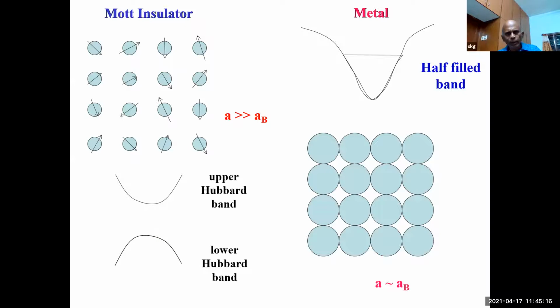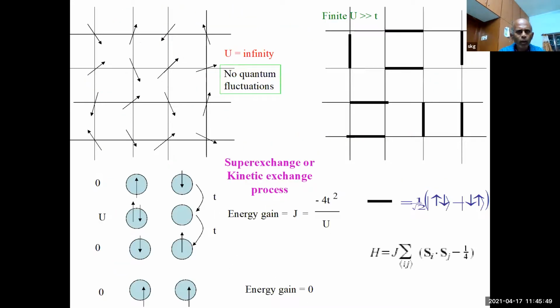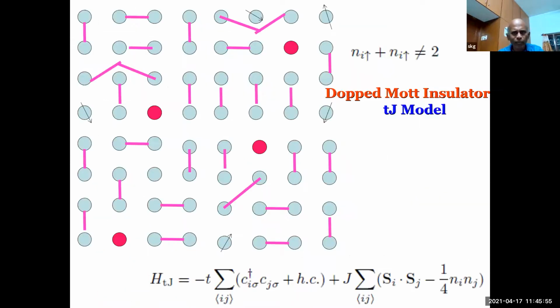So this is something that you're all familiar with. Suppose you take this Mott's argument. Suppose you take sodium metal and keep them very close so that the distance between two atoms is close to Bohr radius. The wave function overlaps. You'll have a beautiful half-filled band. Suppose you do a thought experiment in which you expand sodium metal. Then when the lattice parameter becomes larger than Bohr radius, electrons won't like to form a narrow band, because they tunnel and form a narrow band, but they lose a lot of Coulomb repulsion energy. So they will stay home and do singlet pairing through super exchange and so on. That's the content of Mott insulator and RVB physics.